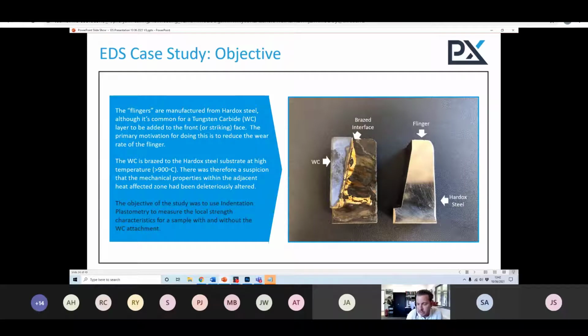Okay, the challenge here, though, is that that brazing process is done at very high temperature, over 900 degrees, and it's over a prolonged period of time as well. And there is a concern, quite rightly, that that brazing process, and therefore that heat treatment, was deleteriously affecting the mechanical properties of that steel, and therefore possibly affecting the wear life of the steel, which would be life limiting again. So the objective of this particular study was to characterize the strength characteristics of these materials using indentation plastometry, because it simply wasn't possible to do this using conventional tensile test machines.